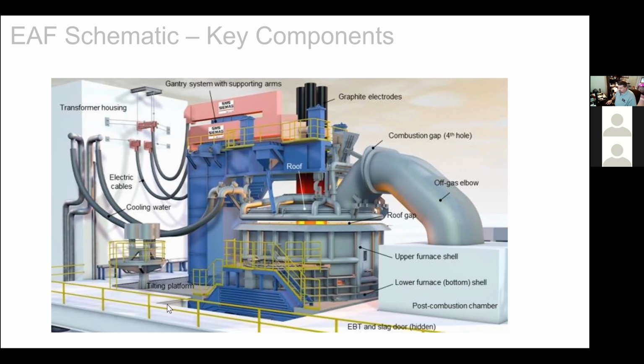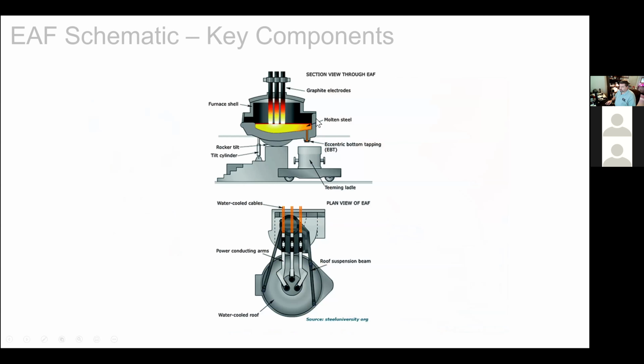So to start a heat, this roof actually swings laterally. And that allows us then to drop scrap into the shell. And the shell is very interesting. The upper portion is water cooled, and the lower portion that actually provides the containment for the liquid steel is refractory lined. So this would be the lower shell here, and the upper shell is water cooled, and the roof is also water cooled.